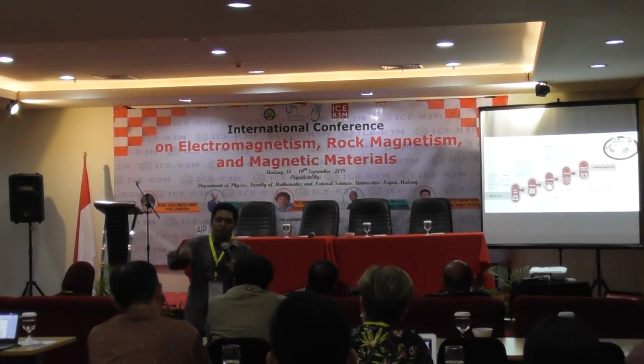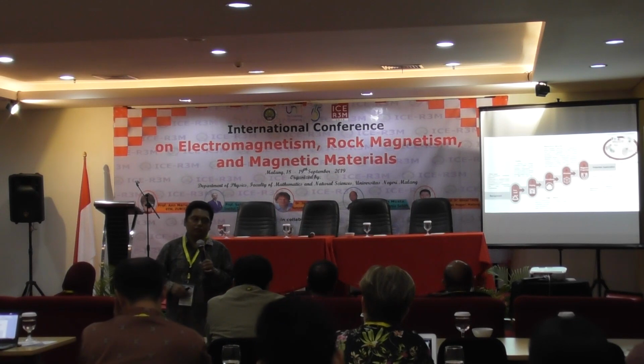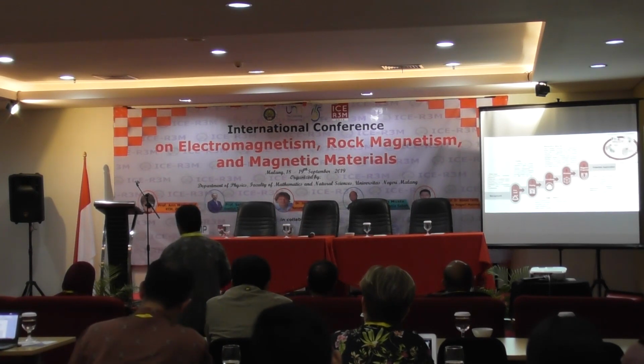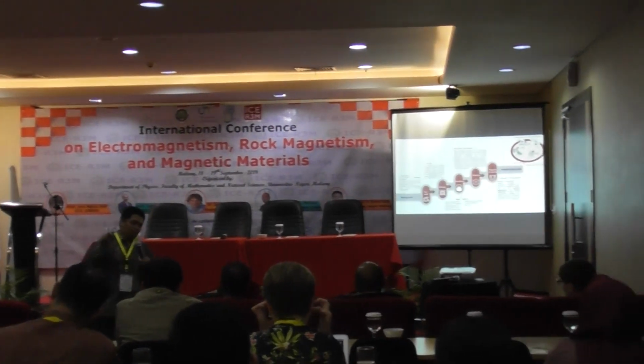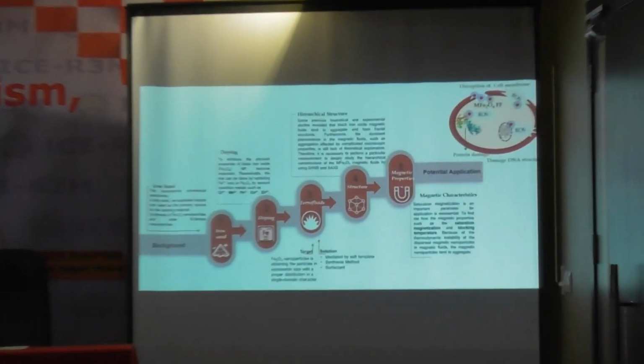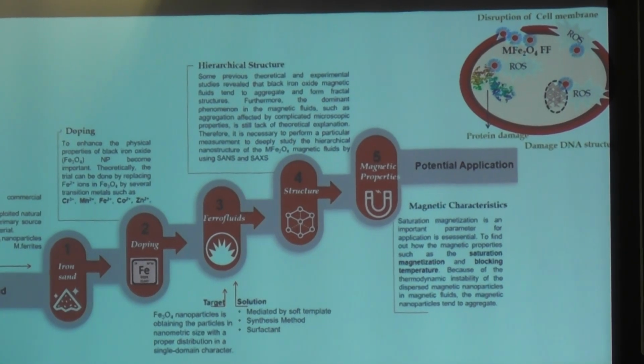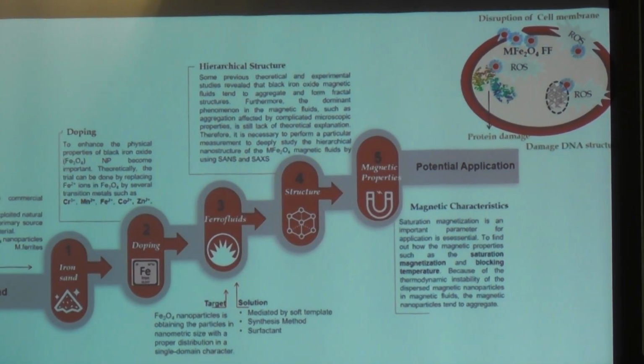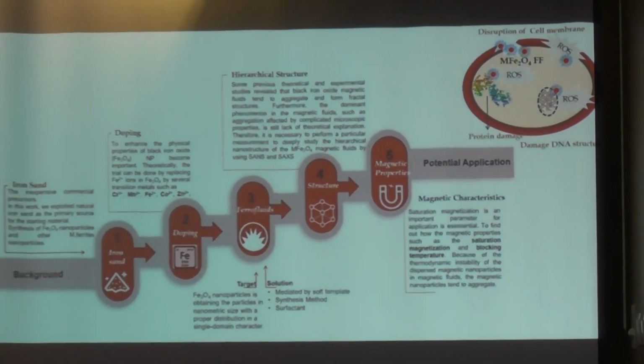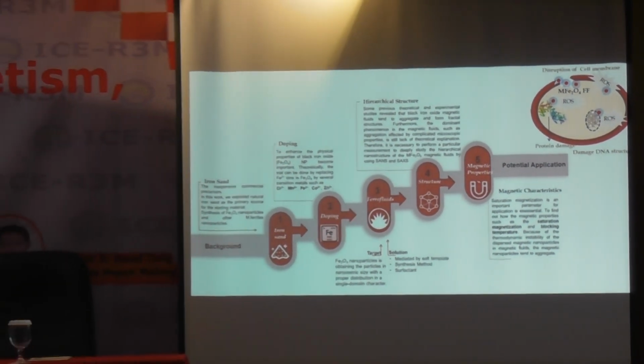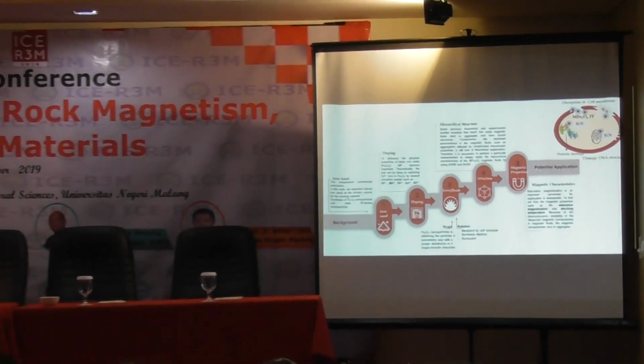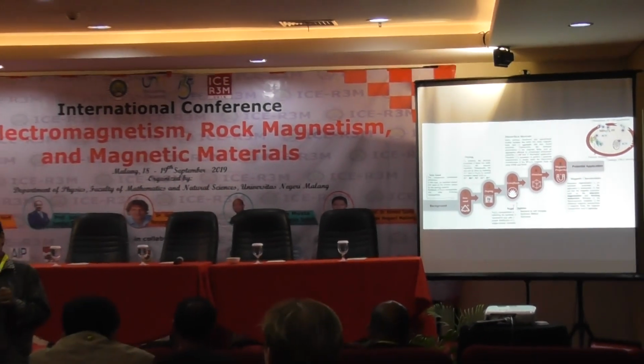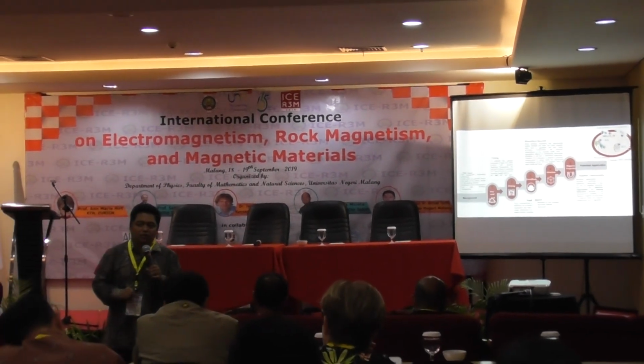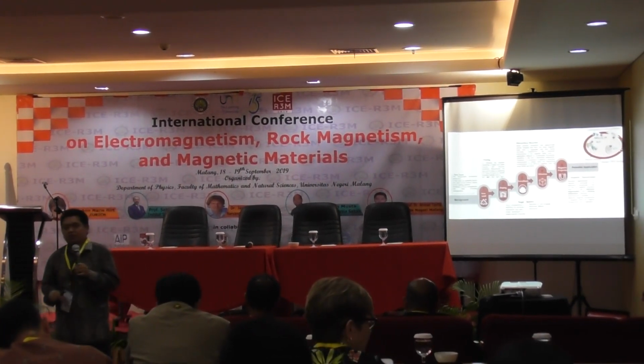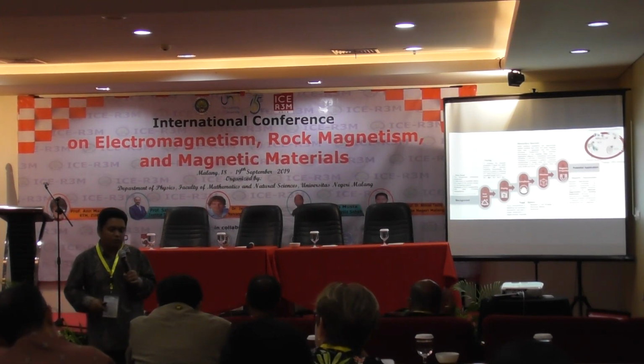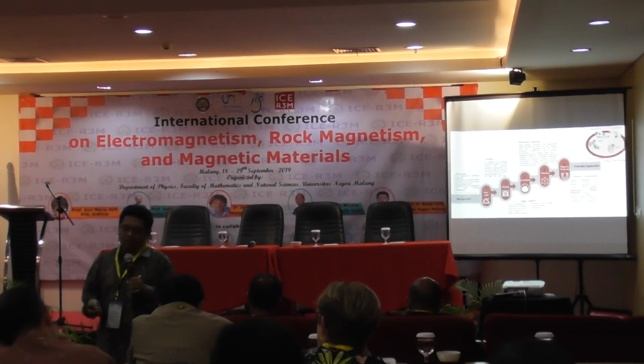We can characterize using transmission electron microscopy, scanning electron microscopy, or atomic force microscopy. But the problem is, for magnetic fluid or ferrofluid, we have difficulty because we should prepare the sample in situ. If we dry the ferrofluid, the fundamental character like the hierarchical structure is not the real character. So we need advanced characterization using synchrotron or neutron, which we have already done in Japan and at Batan in Indonesia.